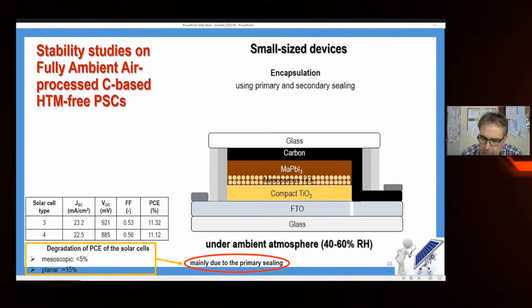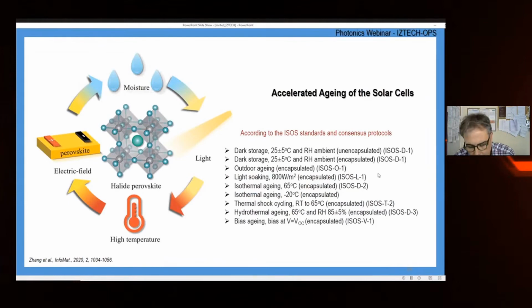I would say that the problem, as I referred, is recognized to be from the first stage when we put the thermoplastic material. Of course, if you want to transfer this technology to commercialize it, you need to pass some tests. These are some of the tests to which we have exposed our devices. They are internationally accepted ISOS standards. We perform several of them in order to be sure that everything is working properly after a period of time.